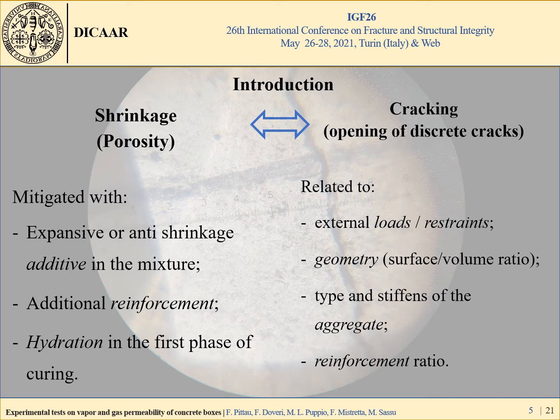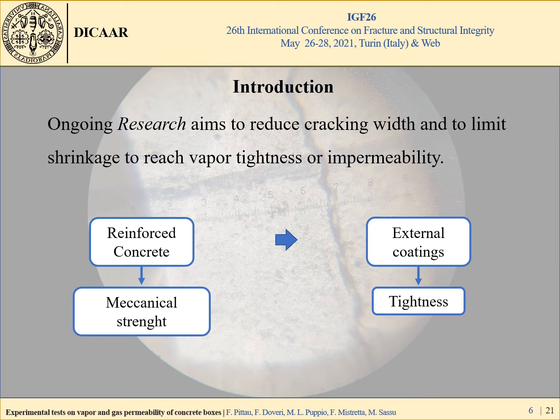Shrinkage and cracking are nowadays considered intrinsic properties of concrete structures with which the designer has to tackle during their work. Shrinkage, also called hygrometric porosity, derives from the curing of concrete. In time, several studies analyzed the use of anti-shrinkage additives that can reduce the phenomenon. On the other side, cracking formation is an element that is strictly inherent to the theory of reinforced concrete. Cracking depends on the elements listed here, for example external load, geometry, type and stiffness of aggregate, and reinforcement ratio. Ongoing research aims to reduce cracking width and to limit shrinkage to reach vapor tightness or impermeability.